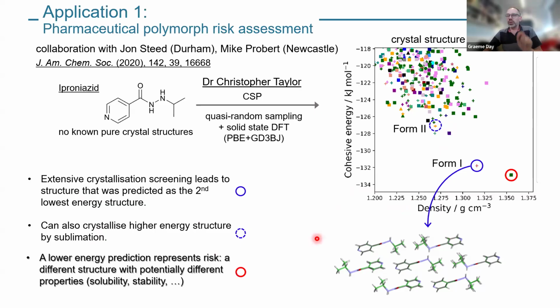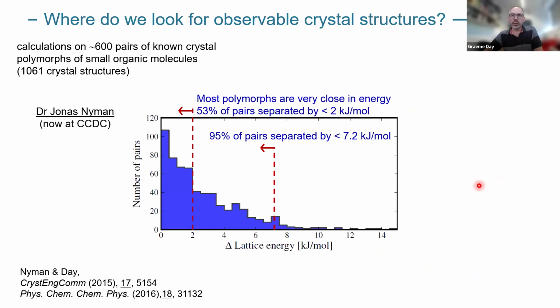But this is a pharmaceutical, and something which really scares pharmaceutical material scientists is when you see something like this. We have a prediction of what looks like a lower energy structure, and it's not being found in the lab yet. So the worry then would be that if you scaled this up and you relied on knowing what the properties were of this form 1, then you get a change in properties if suddenly you started converting to this more stable form. So we decided to do more experiments and also some more calculations.